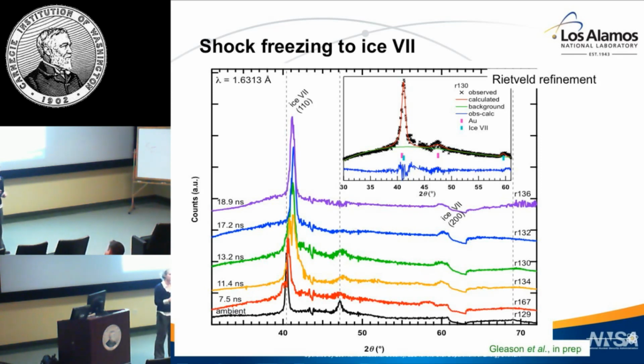Gold with foil? Is it a foil? It's deposited. So if you're getting at a porosity issue, there is a little bit of porosity, but at these thicknesses it's fairly negligible. And texture? There is a little bit of texture. That's right, so that's included. You can incorporate texture components into the Rietveld refinement. I didn't find that it was so pronounced with the gold at this deposition, but that is an issue for other deposited metals, absolutely.